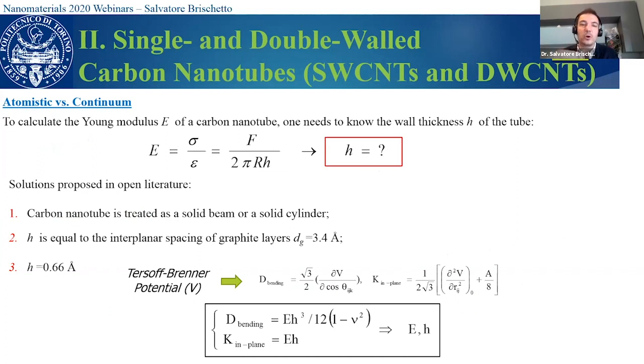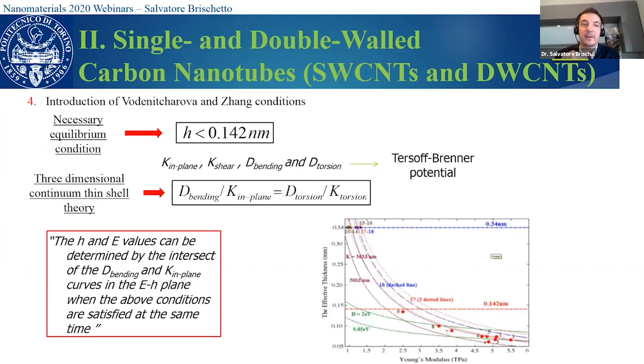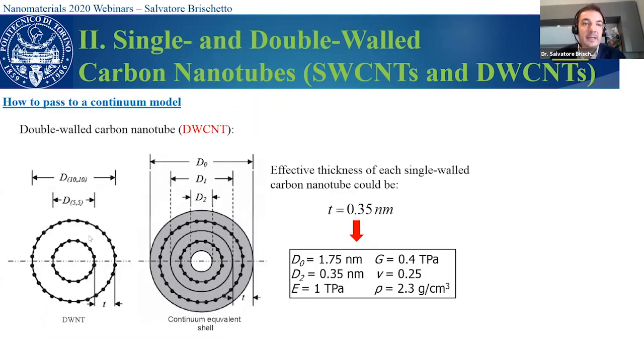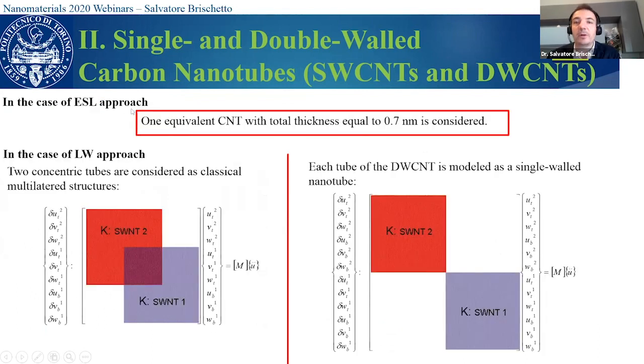One of the possibilities is to use the Tersoff-Brenner potential, where we link the bending stiffness with the in-plane rigidity, and we consider also this limit. 0.142 nanometers is for equilibrium conditions, and then from all this system of equations we obtain appropriate values for the Young modulus and the equivalent thickness. In the case of double-walled carbon nanotubes, there is the same problem, so we must define a first thickness for the first concentric carbon nanotube and an appropriate thickness for the other concentric nanotubes. And after this, in case of equivalent single layer approach, we can consider a double-walled carbon nanotube as only one carbon nanotube with the total thickness 0.7.